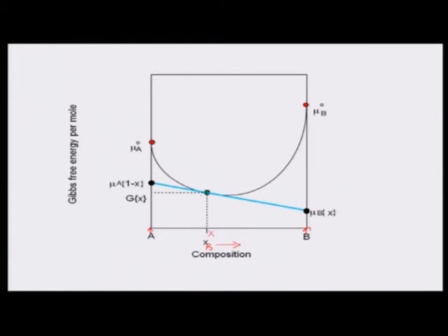So in that case these two ends will give you the chemical potential of A and chemical potential of B. Now if we consider this is for, suppose, phase alpha, this is the free energy of alpha, and this is how the chemical potential can be measured easily graphically. Why is it the tangent to the curve rule? That also needs to be discussed, we will discuss later why the tangent to the curve gives you the chemical potential of the two components at the ends.